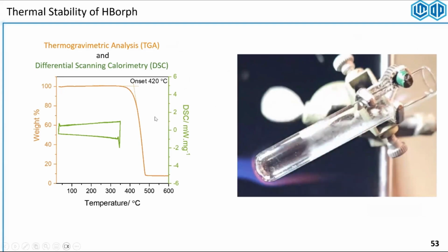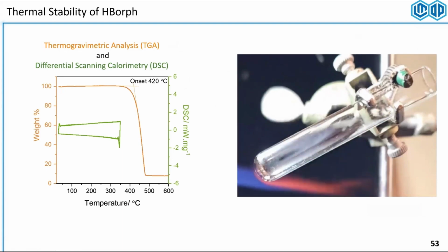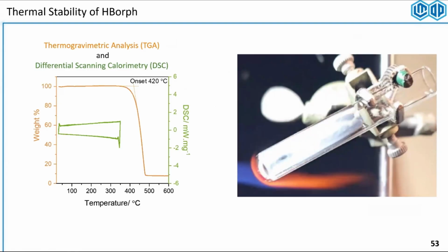Surprisingly, it was very stable. So even though the precursor looked very fragile to work with, once the macrocycle forms, we could just put it in a test tube, heat it up with the torch in air, and it makes this nice white smoke, which you might think is burned, but it's the macrocycle turning into a crystalline fog that then sits on the walls of the test tube.